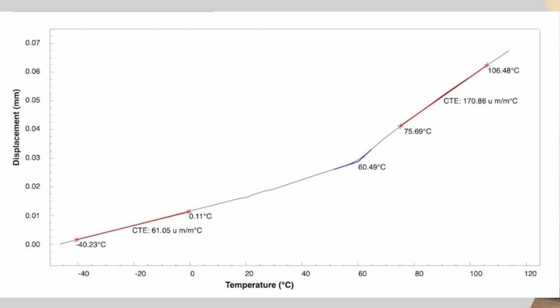To the right of the TG, you see the post-TG CTE, measured between 75 and 106 degrees C at 170 ppm. The post-TG CTE is typically higher than the pre-TG CTE. It is important to understand where the TG of the polymer is relative to your operating temperature range to reduce component stresses that occur in this thermal transition.